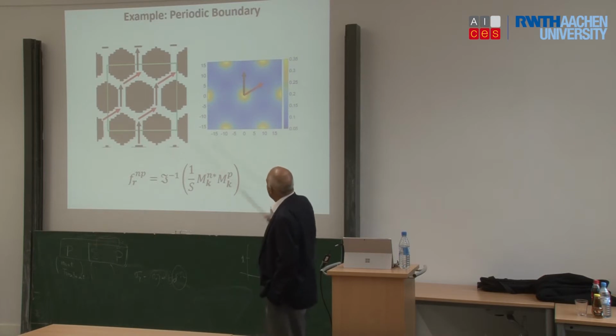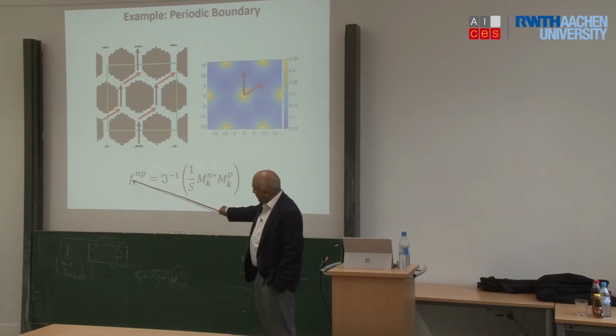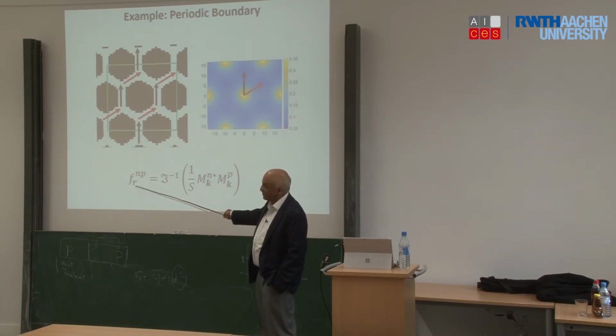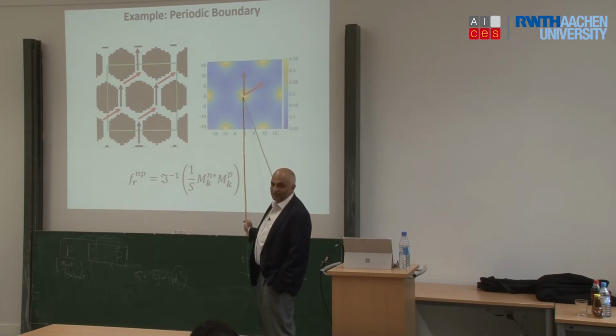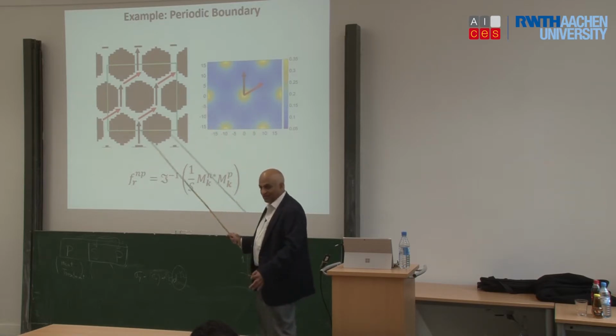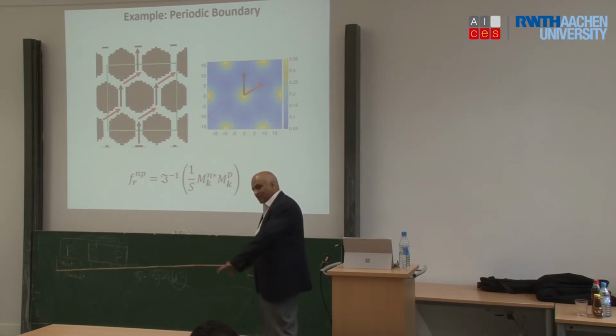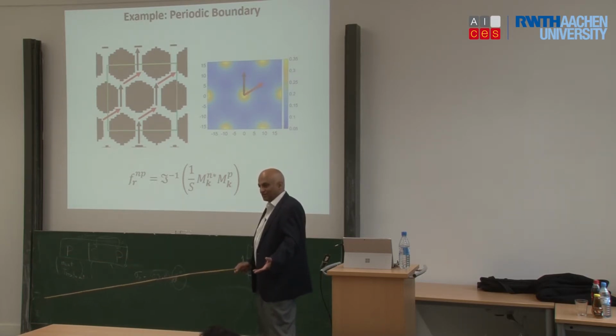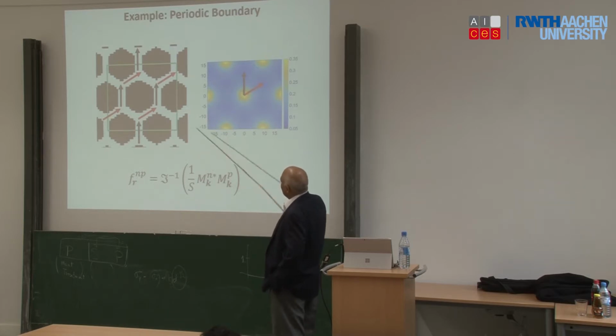It has volume. The one that is obvious is the center, because the center is the probability of finding this particular state at the 0 vector. So that's nothing but, in the eigen microstructures, when you have zeros and ones, the center is always the volume fraction. So the 1-point statistic like volume fraction is always embedded in the 2-point statistics, and 2-point statistics are always embedded in 3-point statistics. They're always there, so you don't have to come back and do it again. Okay? But there's all the information.